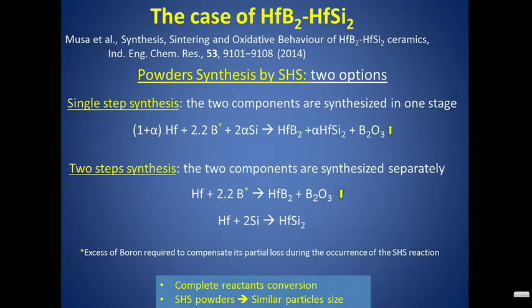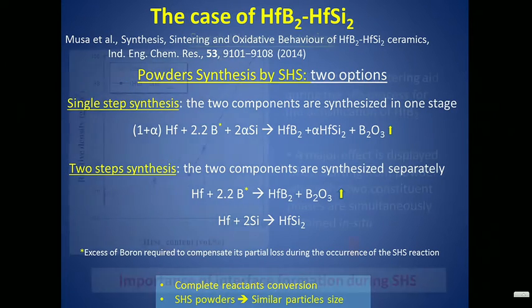Let's take a look at another system. Here you can produce the powder in two ways. You can go directly to obtain the two components in one stage, or you can have a two-step synthesis, in which you synthesize the two components separately. Just note that there is an excess of boron in the mixture, and this is required because there are certain losses during the SHS reaction. So basically, in both cases you complete the reactant conversion, and you get powders with similar particle size.